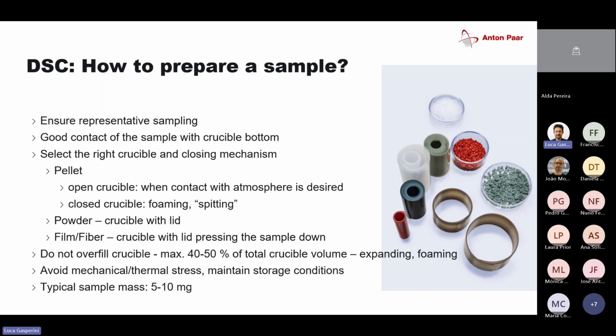And then some more general advice. Do not overfill the crucible. Use maybe 40-50% of the total crucible volume to allow for the expansion and foaming, and avoid the sample actually creeping out of the crucible. Sometimes it's important to avoid mechanical or thermal stress, because even tiny changes in mechanical preparation of the sample can induce changes in the glass transition, for example.